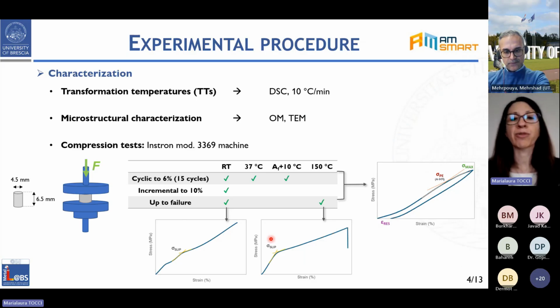The characterization carried out is listed here. So we perform DSC analysis to investigate the transformation temperature. We perform a microstructural characterization with optical and electron microscopy, and we then investigated the superelastic behavior using compression tests under different configurations. So we perform cyclic tests up to 6% deformation with 15 cycles at different temperatures: room temperature, 37 degrees Celsius to reproduce the body temperature, and, in order to compare materials in the same thermodynamic state, a temperature that's 10 degrees above the austenite finish temperature. Then we perform incremental compression tests up to 10% strain, in this case only at room temperature.